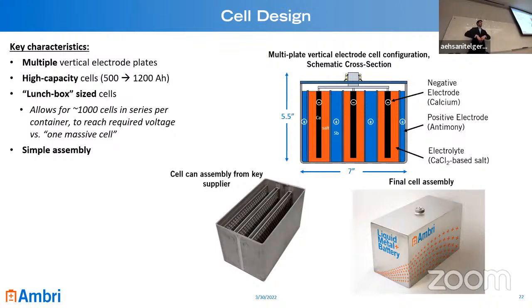And so why doesn't that just float up and rest on the top of the cell, because it's lower density? That's where a lot of the IP and nuanced design is. But metal likes to wet other metals. There's a preferential wetting of metal onto metal compared to salt onto metal. So as you're depositing the calcium onto this porous metal negative electrode, it's like water into a sponge. It gets sucked in and is held in place through surface tension. Thank you. Yeah.